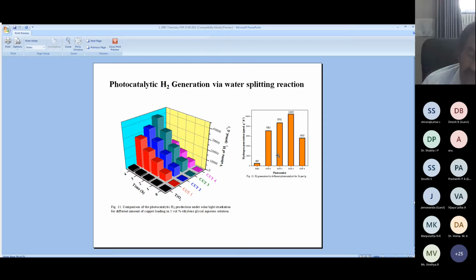When we did the hydrogen generation for that, pure TiO2 generates, they have mentioned, 493. As the percentage of copper increases, right, the hydrogen generation also increases. Interestingly, at 3% copper doping, we got very high H2 generation. As the percentage of copper increases further, hydrogen generation decreases again.